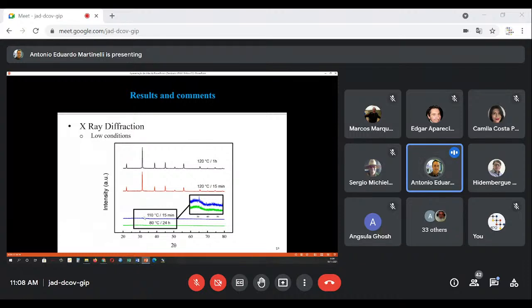These are the lowest temperatures used. At 80 degrees Celsius, we couldn't see the formation of barium titanate. At 110, we see just the start of crystallization of the phase. But it's interesting to see that when we go from 110 to 120 degrees, just 10 degrees, now at the same time, we see the formation of barium titanate, and we don't see any other crystalline phase. Of course, here we don't have 100% crystallinity, as I'm going to show you in the pictures, but we see single phase formation during the whole temperature and time range investigated.